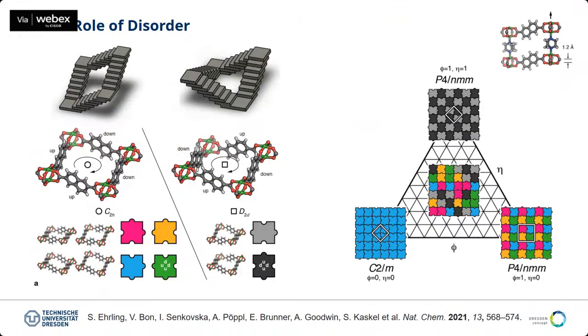Here, right? Yeah. So I think this was also my theory in the beginning, that the whole system is dynamic and that the linker is always rotating. But the NMR results show that this is not the case. So it's always a stepwise transformation once you change the solvent. There's a small flip movement, but there's not a continuous rotation.